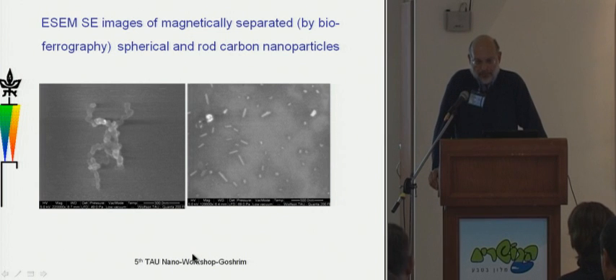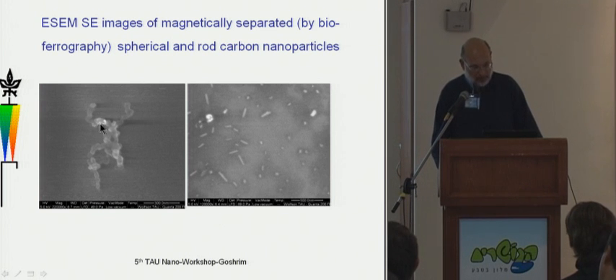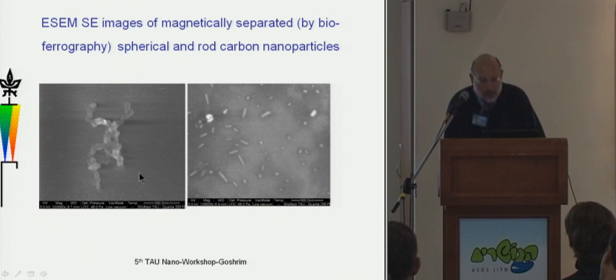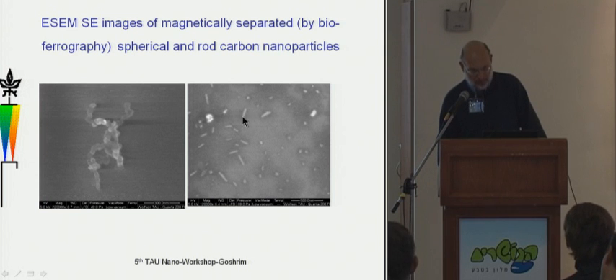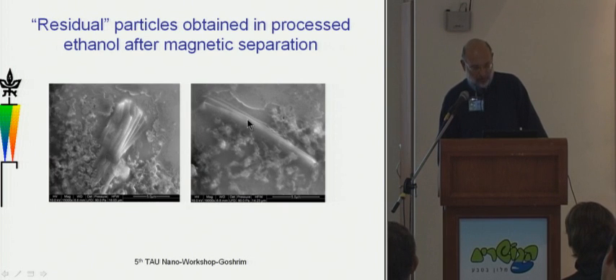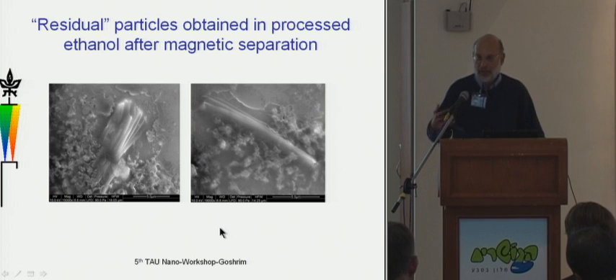And then we looked at the separated magnetic particles from the ferromagnetograph, and we found that there were basically two kinds of particles there. There were agglomerates of more or less spherical particles, and the scale length here is 300 nanometers. So these are nanometric sized particles. This is the scale here. So these are in the range of 10, 20 nanometers. And some kind of short nanorods or nanotubes. On the other hand, if we look at the residual material, what passed through the ferromagnetograph without being collected, we found all kinds of other shapes and typically larger sizes.